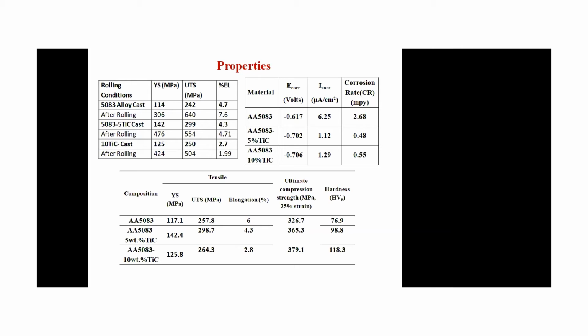If the reinforcement is a bigger size, it changes the solidification pattern of the cast during casting, but finer doesn't create any problem, and we can easily roll it, because these particles won't create any problem for the dislocation motion. And if we compare, you can see that tensile and ultimate compression strength also enhance for this composite, and hardness also increases, so you can use it for tribological properties.